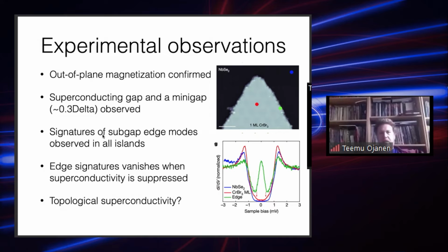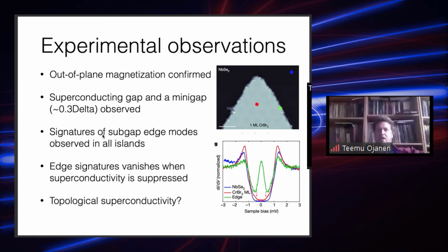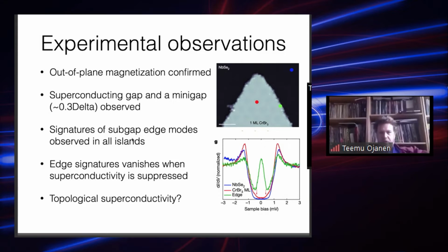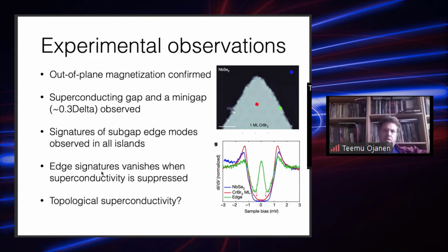So this is not a hand-picked example of a single island, but a generic feature in all islands, and that's why it seems to be a very robust feature, which is of course very important. And also this edge signature, this enhancement, is vanishing when the superconductivity is driven out of the system by increasing magnetic field. So when superconductivity disappears, this type of subgap enhancement is also killed. So that's also, of course, a good sign for this phenomenon to be topological superconductivity.